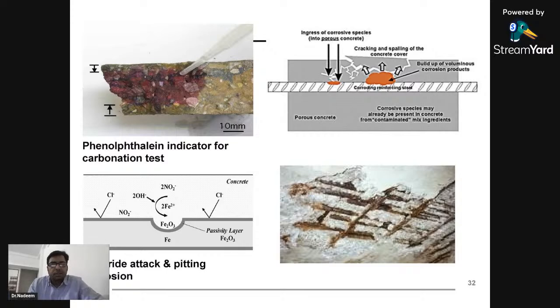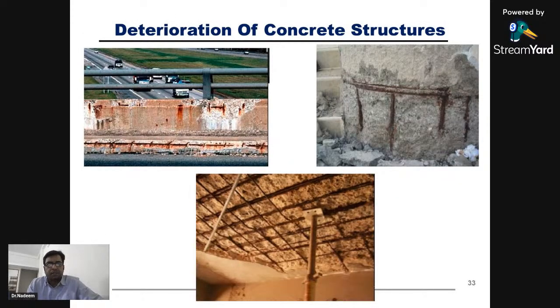And subsequent reactions happen in the form of carbonation or corrosion of reinforcement. Once the carbonation layer is disturbed, naturally it becomes acidic. And once chloride and water ingress happens, corrosion starts in the reinforcing steel. This is the deterioration of the concrete structure. Once corrosion starts, it swells to 5 to 6 times its original volume, and it creates a lot of pressure on the surrounding concrete. Initially cracks happen and then spalling of the concrete starts. So this deterioration happens if the permeability and porosity are not addressed, maybe after 5 years or 10 years down the line.